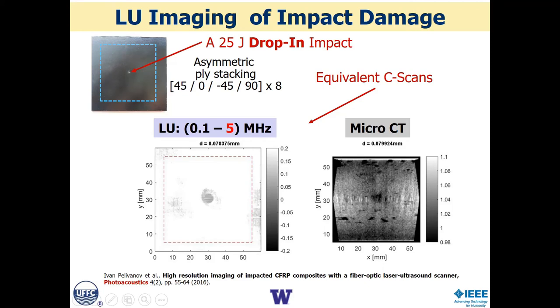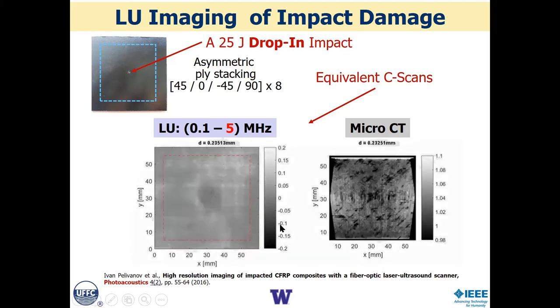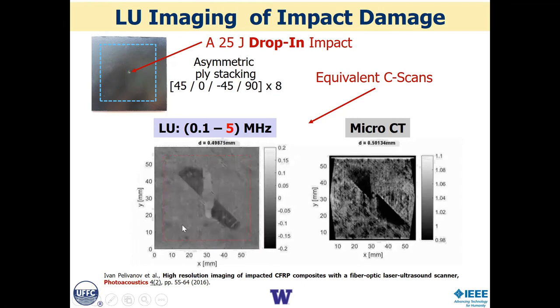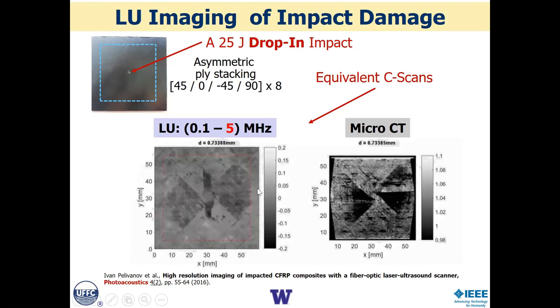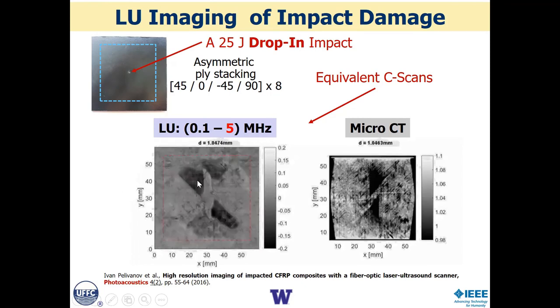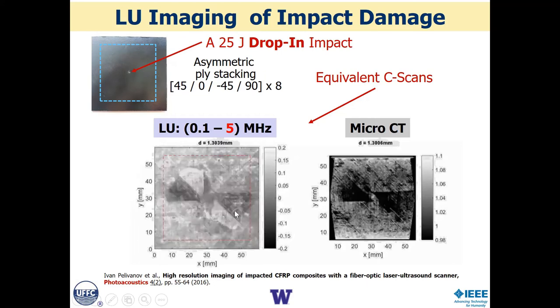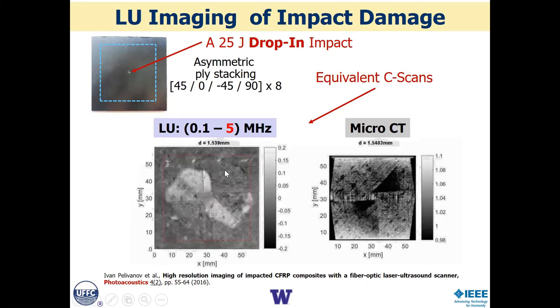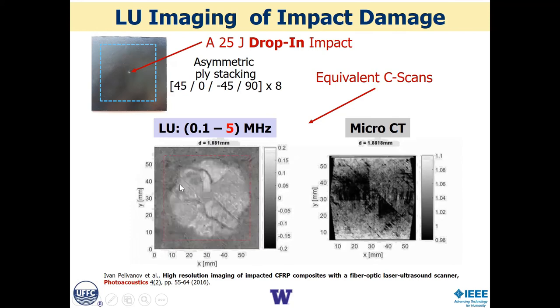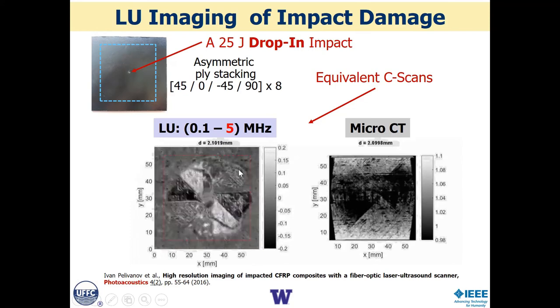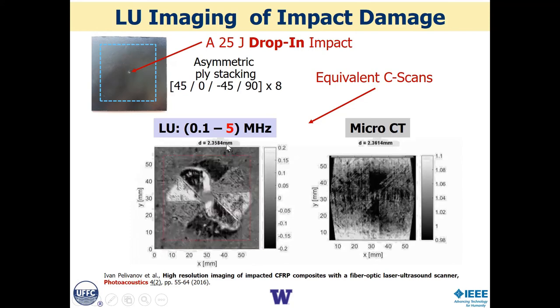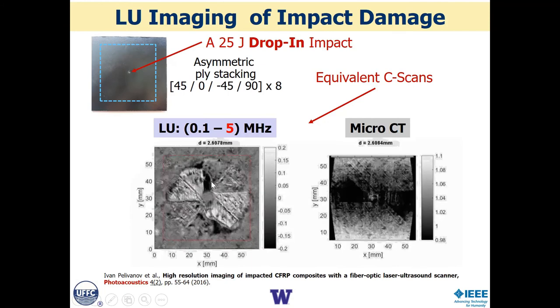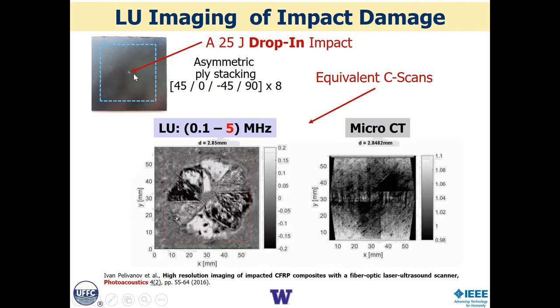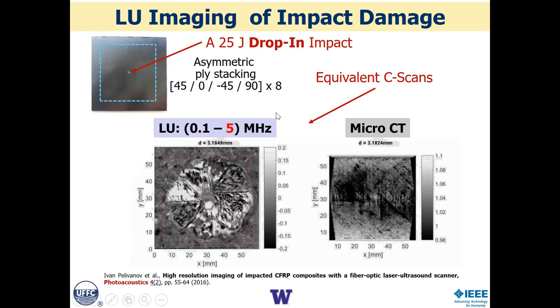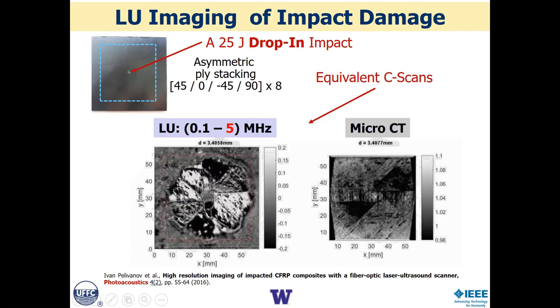So I'll play the movie and you can look through. Now you can see these propeller effects, which we see both on the CT and on the laser ultrasound. And here in the laser ultrasound, we let all of these integrate together because you get reverberations of the sound. So you can see the entire volume of the damage, a huge volume of damage for that little surface defect. Now I think you see the power of this, and that's why the Boeing folks were so excited.